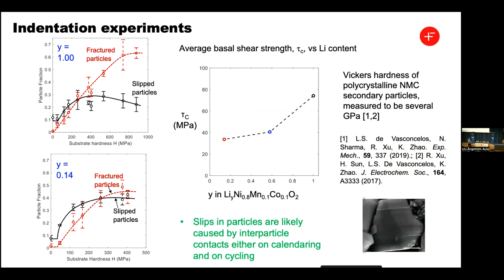And you can see that on delithiation that force decreases, and it's a very low force even at the fully lithiated phase. So putting the two together, it really becomes clear that the images that you see of these slipped particles are not coming from the cycling. They're coming from the calendaring processes, or particles hitting each other as everything is expanding and contracting in the electrode.